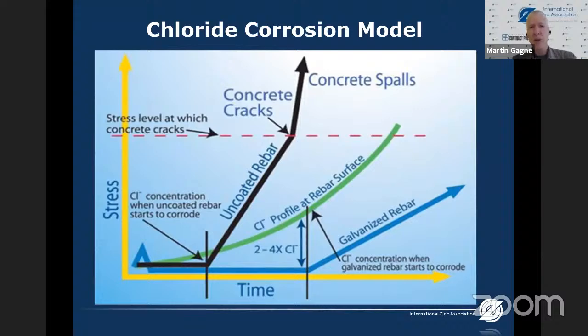I'm going to go more in depth on this chloride corrosion model, although we've seen it already. If we look at the yellow line here on the left-hand side for stress, the stress builds up until it gets to a level where the concrete cracks, and that's represented by the dashed red line. The yellow line at the bottom, the horizontal line, is the time scale. So we see the black uncoated, and then the green line is the chloride profile at the rebar surface.